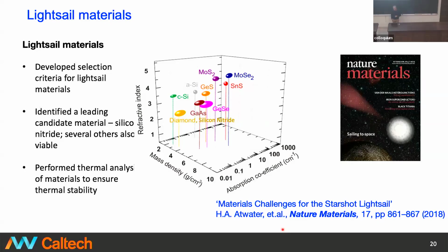In this case, because of the need to accelerate the light sail kinematically, we're interested in something that has a reasonable mass density. And then in order to get good reflectivity, you like to have a material that has adequate refractive index. We can use photonic design to compensate for that to some extent, but just the index contrast between vacuum and the material itself generates a significant advantage in terms of generating high reflectivity materials. So this is sort of a suite of materials that were considered.